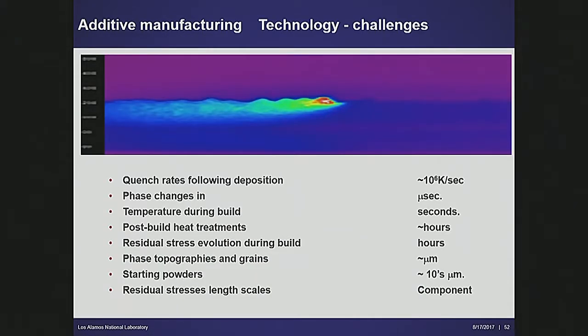The challenges in doing this derive from the fact that quench rates in additive can be as much as 1 million degrees a second. Phase changes, temperature builds, phase topography, starting powders, right? You've got a whole series of phenomena here that change from microseconds to hours and from microns to the scale of the component. And so,